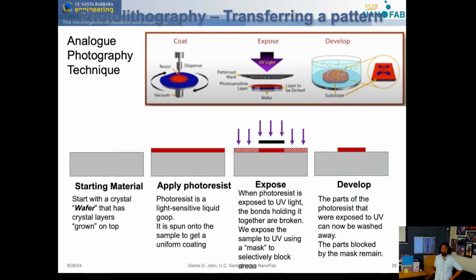Okay. I will say there are, just like having 7 or 8 different types of saws for woodworking, 7 or 8 different types of patterning tools at the NanoFab. Some are very fast, but can only do larger features. Large, by the way, in the NanoFab means like 200 micrometers or 50 micrometers. A human hair is about 100 micrometers, and we call that big, which means it's super easy to do 50 micrometers. I don't even think about it. We just do it, and it basically works. And then you have other tools that are very, very slow, but can do 2 nanometer level patterning, right? So that means this resist area might literally be 20 molecules wide. So you pick the right type depending on what you're trying to do.